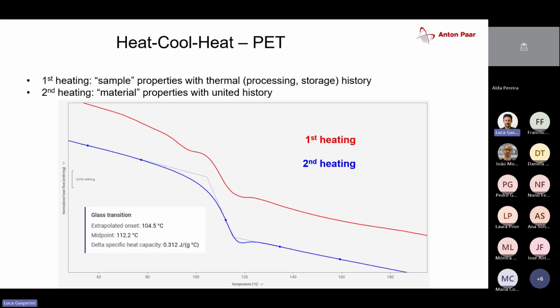One of them is a heat-cool-heat, so a repeated heating. First we heat the sample, then we cool it down with a defined cooling rate, and then we heat it again. Why do we do that? During the first heating, we would see sample properties with all the thermal history, or processing history, or storage history, where what we do with the history during the first heating and cooling, we either delete it, erase it, or we unite this history, meaning that the second heating gives us the actual material properties with the united history.